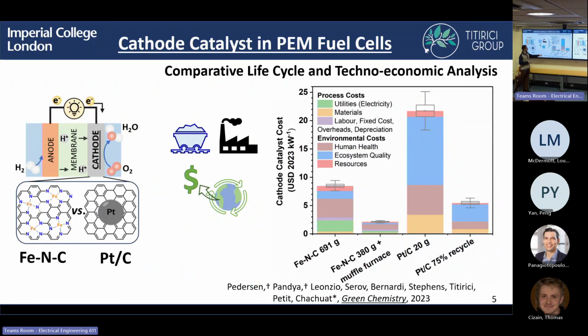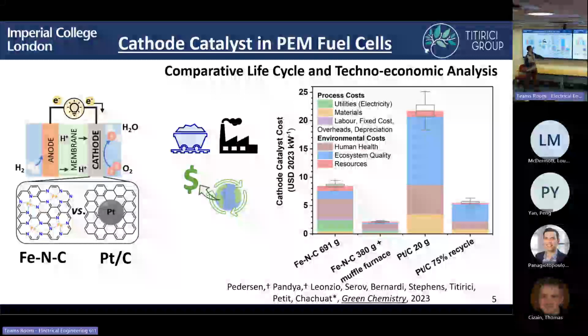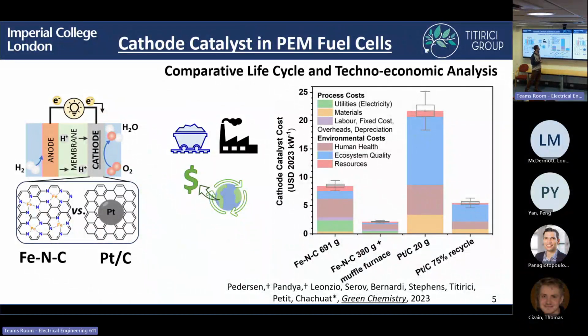So here you can see a summary of an analysis that we did where we compared a platinum carbon catalyst, where typically you have around, say, 20 grams or 10 grams of platinum in a fuel cell car, and the equivalent amount of iron nitrogen carbon catalyst is around an order of magnitude higher. But the cost of producing that catalyst, shown in the green, orange, and purple here, is about the same actually as the platinum carbon catalyst based on current performance. But then if you start including the environmental impact of producing that catalyst, we see that we actually have a much lower environmental cost for the iron nitrogen carbon catalyst, and this is due to mining of platinum having a really significant environmental impact.